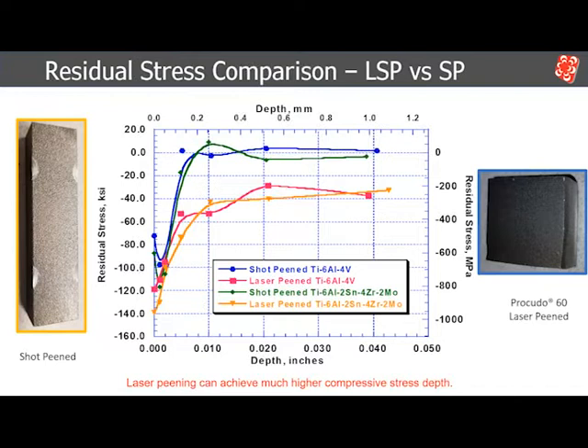So I did show a bit of residual stress, and I didn't explain, are these good? Are these bad? Historically speaking, as with any other mechanical surface treatment, a lot of the original data is compared to shot peening, shot peening being the most commonly used surface treatment in the industry. A lot of Alan's and Jeff's talks touch on that. Historically, laser peening was used in conjunction with shot peening, or in applications where shot peening provides very shallow residual stresses and you need the added benefit from the laser peening process. In most applications, laser peening was used due to the higher depth of compressive stresses that you can generate.